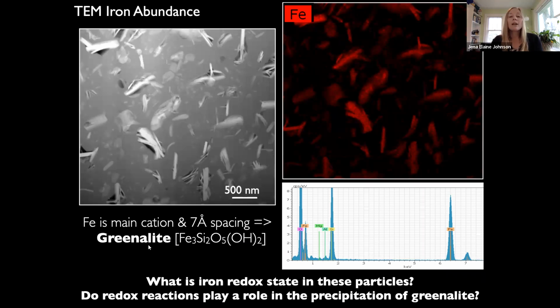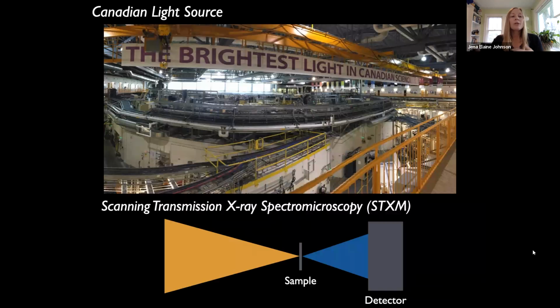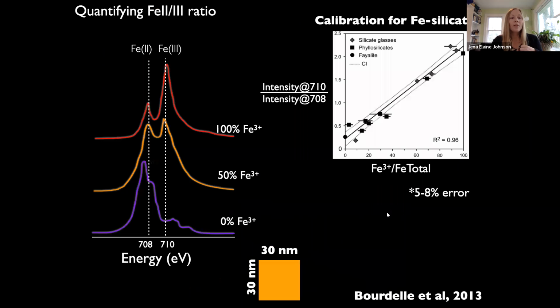Now, we also wanted to measure the redox state of iron in these particles at the scale of individual particles to see whether redox reactions could still play a role in the precipitation of these minerals. So we took TEM sections of chert to the Canadian Light Source synchrotron, to scanning transmission X-ray microscopy, or the STXM, where we can focus only on the iron and measure the iron redox state at a 30 nanometer scale. This technique measures the iron L edge, which distinguishes between iron 2+ and iron 3+. And we used a calibration based on the ratio of the iron 2-3 peak to quantify the amount of iron 3+ present. This was developed by Bourdelle et al. in 2013. And then we rastered the beam throughout the nanoparticles at these key energies to create an iron redox map at the nanoscale.